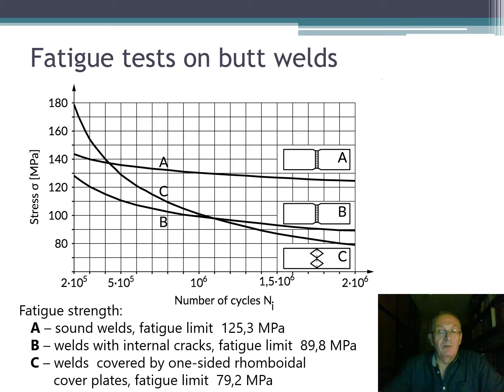Specimen B, welds with internal cracks. Fatigue limit was estimated at nearly 90 megapascal. And C, welds covered by one-sided rhomboidal cover plates. Fatigue limit was estimated at nearly 80 megapascal.